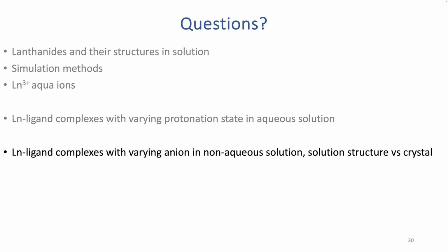You wouldn't need to do the FEFF simulation from all of those, from 200 structures. You could just analyze what is the RDF and what is the RDF that the EXAFS imply. And I get that doing the MD simulation in the end is very helpful, but that might guide you and be a little faster. Yeah, thank you.